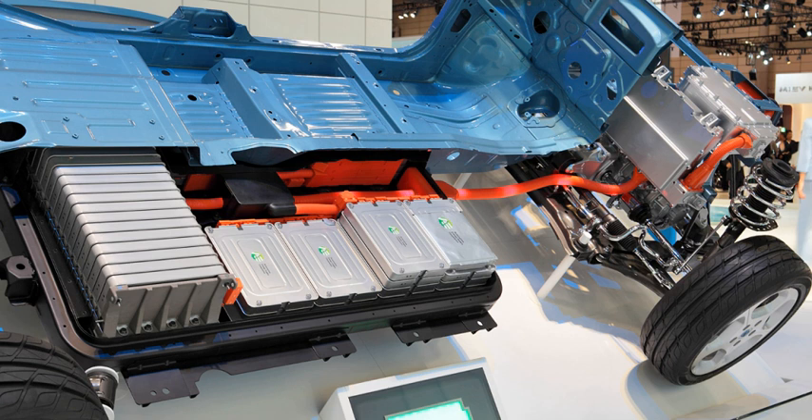Deep cycle lead batteries are expensive and have a shorter life than the vehicle itself, typically needing replacement every three years. Lead-acid batteries in EV applications end up being a significant portion of the final vehicle mass, with significantly lower specific energy than petroleum fuels — 30 to 40 watt-hours per kilogram. The efficiency and storage capacity of deep-cycle lead-acid batteries decreases with lower temperatures, and diverting power to run a heating coil reduces efficiency and range by up to 40%. Recent advances in battery efficiency, capacity, materials, safety, toxicity, and durability are likely to allow these superior characteristics to be applied in car-sized EVs.